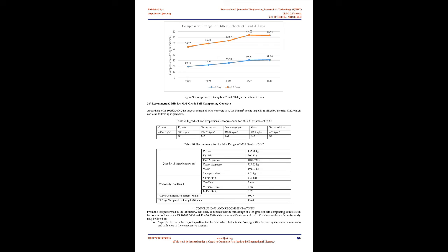as the fresh property. The SCC property started to show its results when the water-cement ratio becomes 0.4. The slump flow obtained between 660 to 750 mm, which falls under SF2 criteria of the EFNARC guideline, which shows that the concrete can be used in normal applications like walls, columns, etc. 5 trials performed during the study meet SCC property as per table 4. Among these trials, FM3 was considered the best mix for the fresh property of M35 grade self-compacting concrete.